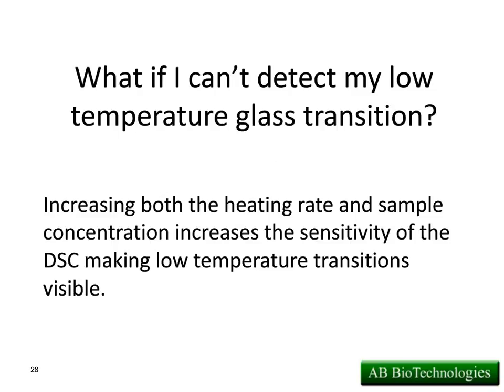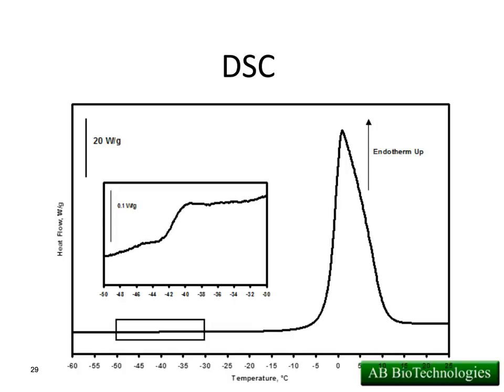Now, what if we can't detect our low-temperature glass transition? Well, we can increase or change the heating rate. Now, what we see here in this graph, when we first ran the graph, you'll see the inset here. Just kind of cover that up or don't consider that. If we run the graph and we just see this one peak, and we say, well, if we take that as fact, it looks here like we can freeze dry about negative 10 below this thermal event, we're going to be safe, but that's not true. If we look back in the baseline, you'll notice there's this low temperature glass transition that's completely going to screw everything up with our formulation. So again, glass transitions are very low energy events. If you don't look for it, you won't find it.